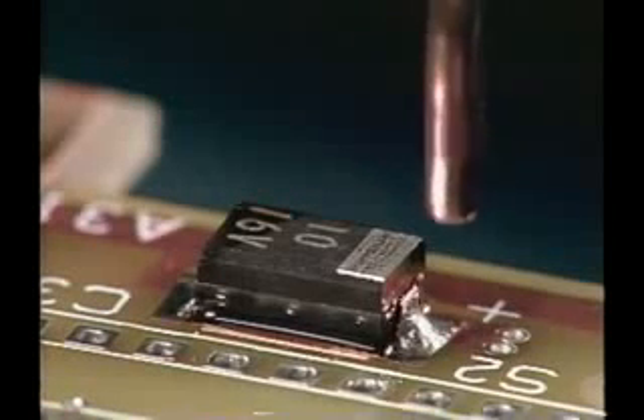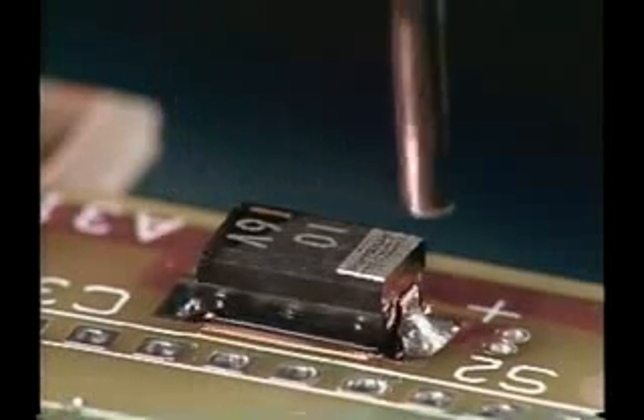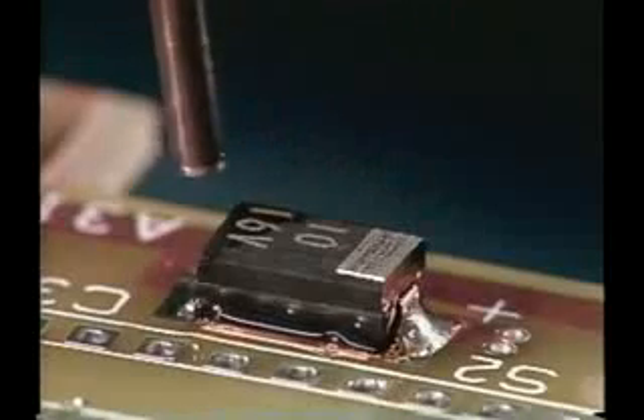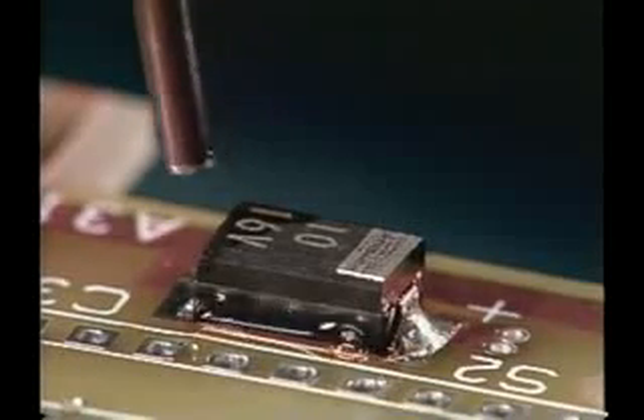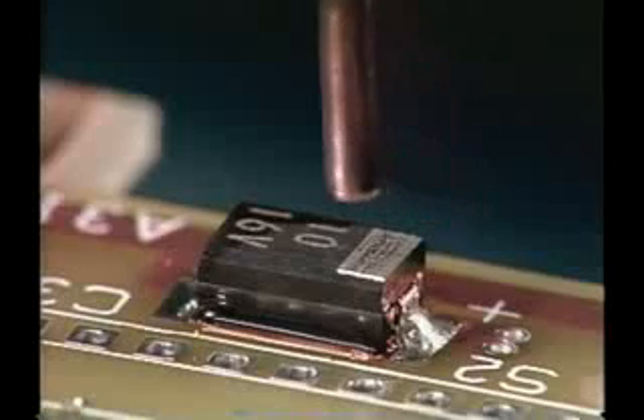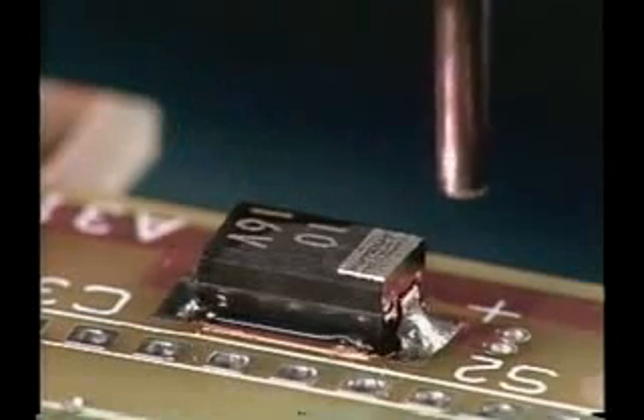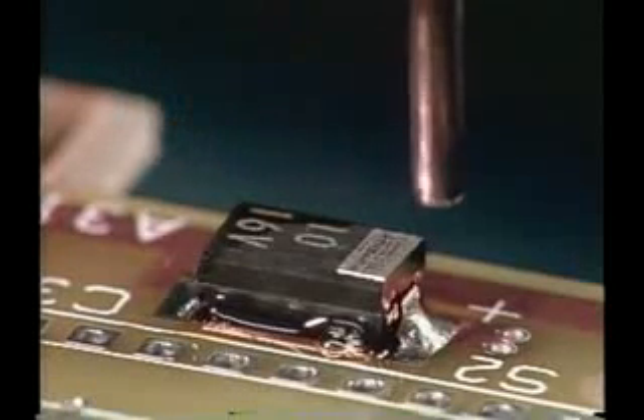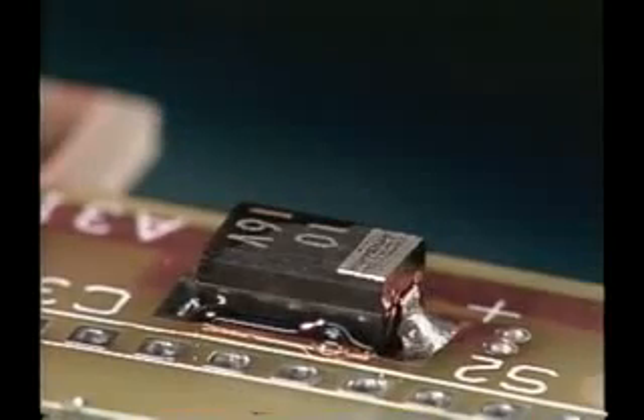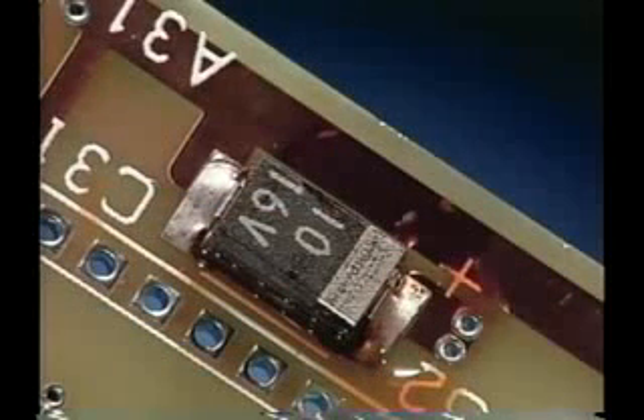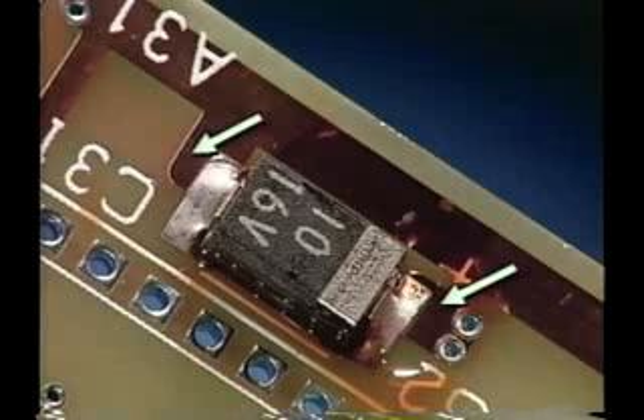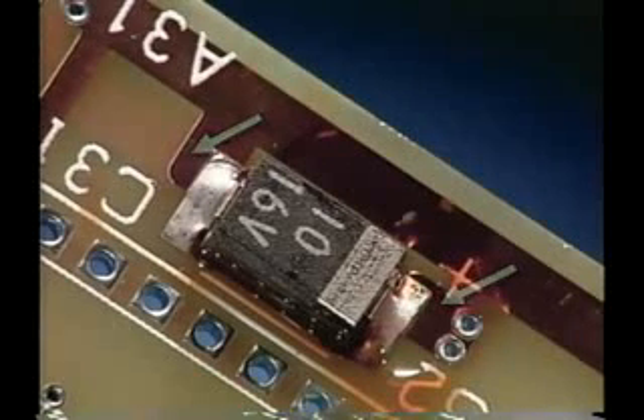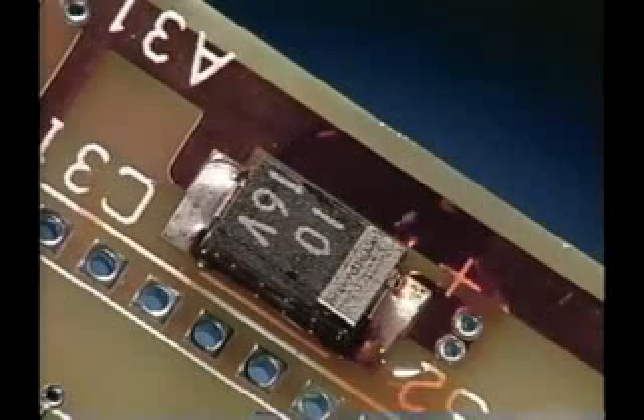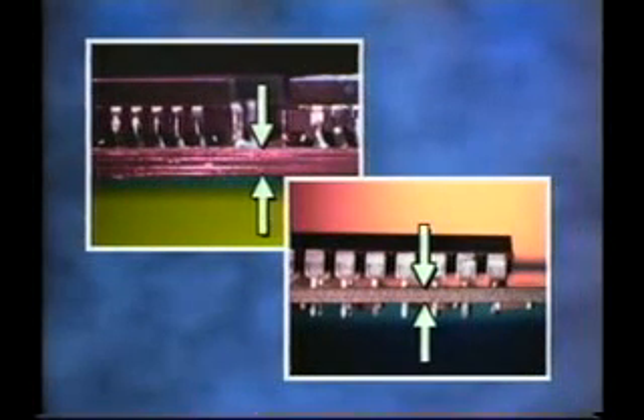Move the tip back and forth to heat both solder joints at the same time. Both joints should melt within a few seconds if the temperature and pressure are properly adjusted. If the solder doesn't melt within 10 seconds, something is wrong. You'll need to stop and examine the situation. It may be a large conductor or ground plane connected to one of the lands. This will require additional heat to be focused on that side. Thick, multi-layer boards will also absorb some of the heat and slow down the process.